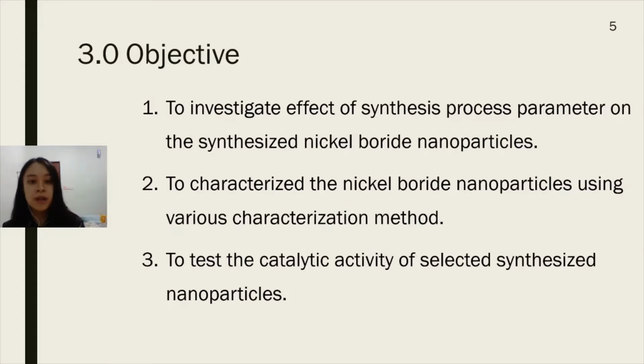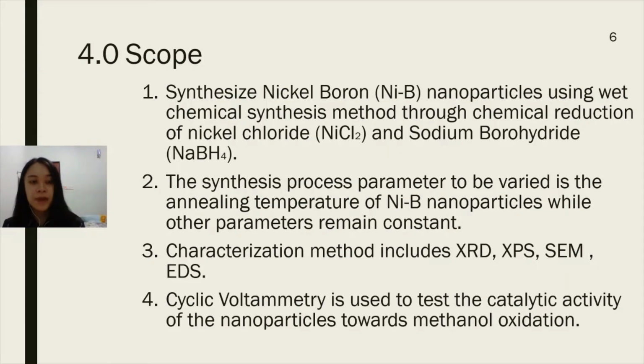The objective of this project is to investigate the effect of synthesis process parameters on the synthesized nickel boride nanoparticles, characterize the nickel boride nanoparticles using various characterization methods, and also test the catalytic activity of the selected synthesized nanoparticles. The scope will include synthesizing nickel boride nanoparticles through wet chemical synthesis from the chemical reduction of nickel chloride and sodium borohydride. The synthesis process parameter that will be varied is the annealing temperature, and the characterization methods used will be XRD, XPS, SEM, and EDS. Cyclic voltammetry will be used to test the catalytic activity of the nanoparticles towards methanol oxidation.